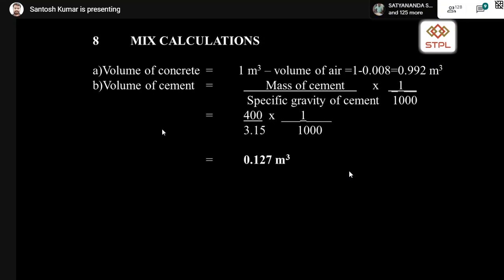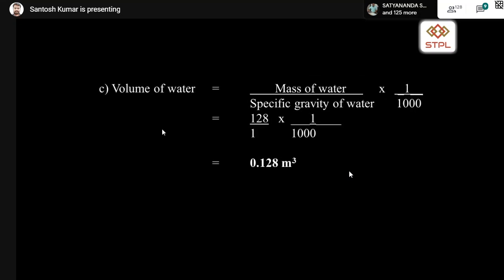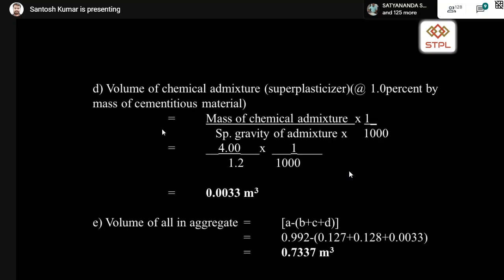So volume of cement comes 0.127 meter cube. That means cement weight by specific gravity of cement, and volume of water is 0.128. Volume of chemical admixture is 0.0033, and the volume of all-in aggregate becomes 0.7337 here. I think it is clear: 0.992 is the absolute volume. From that, you have to remove the volume of cement, water, and chemical admixture. Here there is no microsilica, sir, it is pure cement. So the volume of all-in aggregate becomes 0.7337.